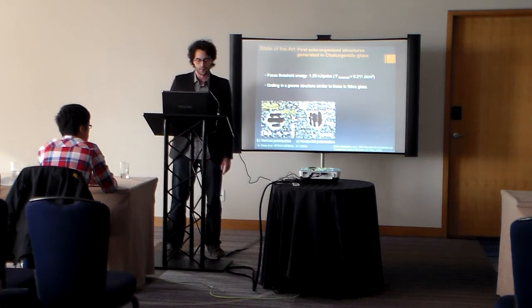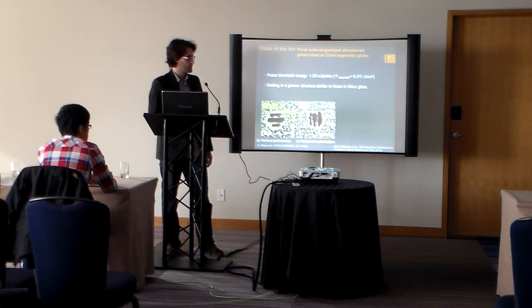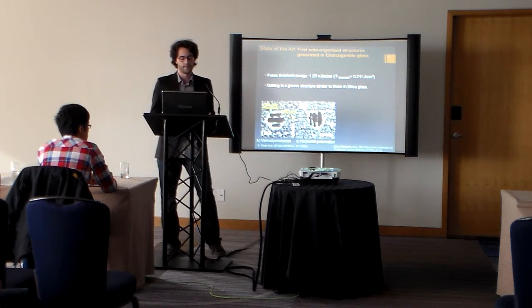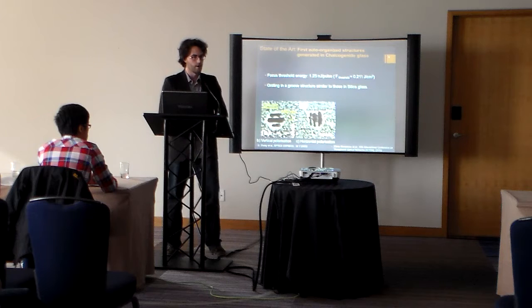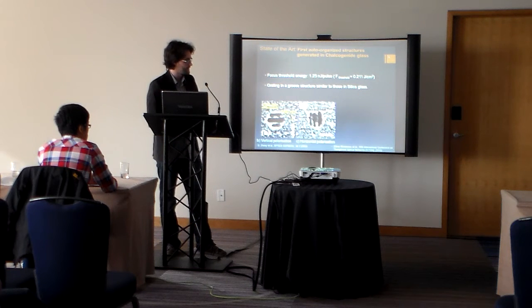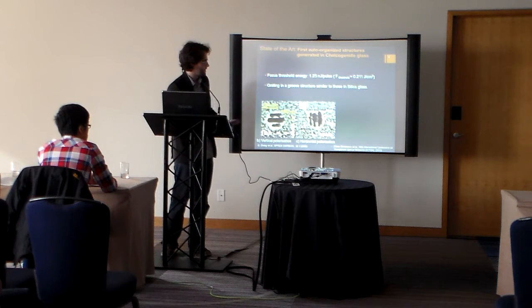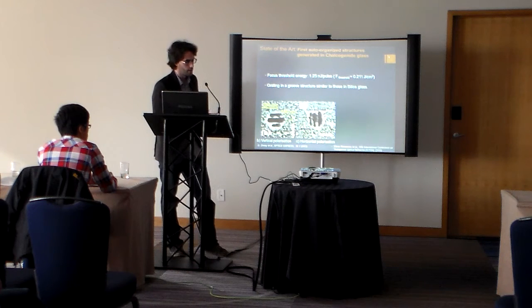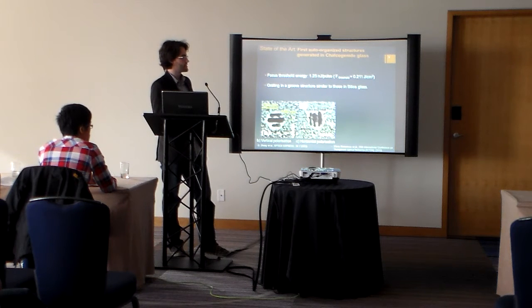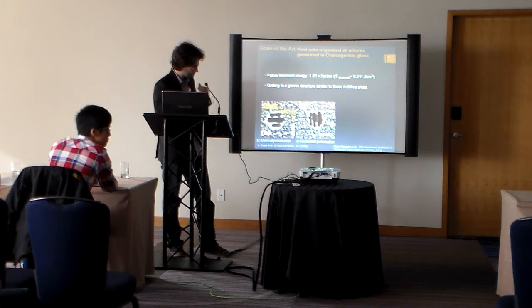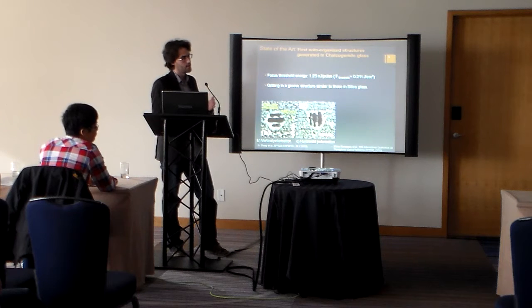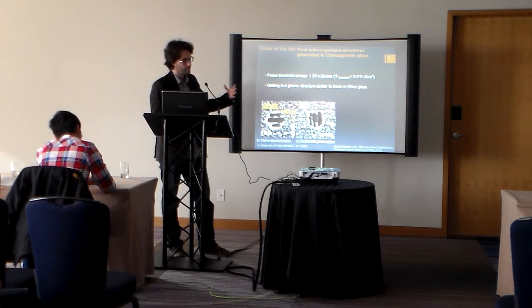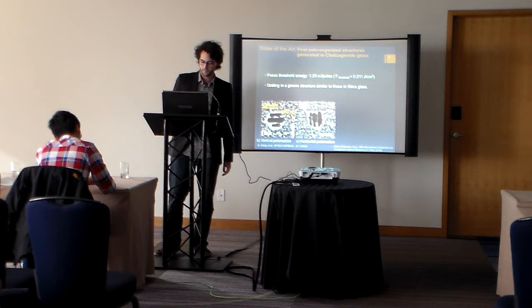The different theory models for the formation of the gratings are not really clear. Basically, the idea is that the plasma created by the pulsed laser interacts with the electric field of the laser. So there's a periodic structure created in the plasma, which creates the gratings on our glass.